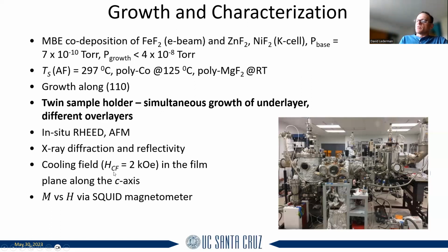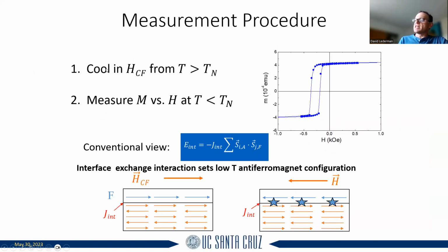So in these experiments, what we do is we cool down our samples in a field through the phase transition of the antiferromagnet, and then you can measure the magnetization versus applied field, and we do have a SQUID magnetometer in our lab that we use for this. So again, the procedure is like this. You cool in a cooling field from above the transition temperature of the antiferromagnet. You measure M versus H. And remember that the conventional view is that, when you field cool it like this, you end up with an exchange interaction here with low temperatures. The antiferromagnet is fixed, at least for low fields, right? So I'm assuming the field isn't super large.